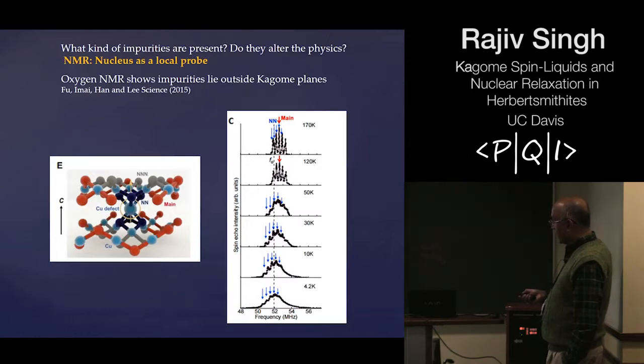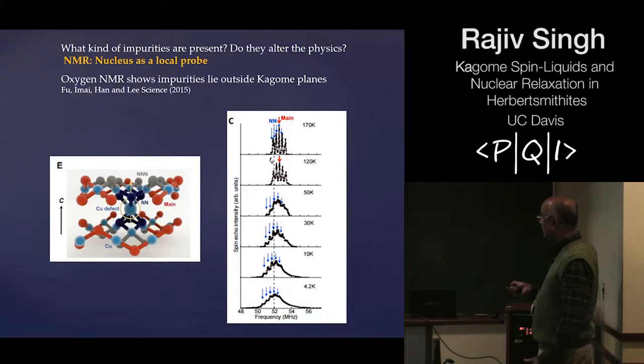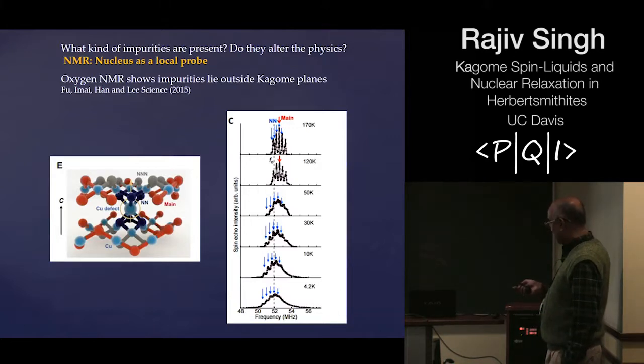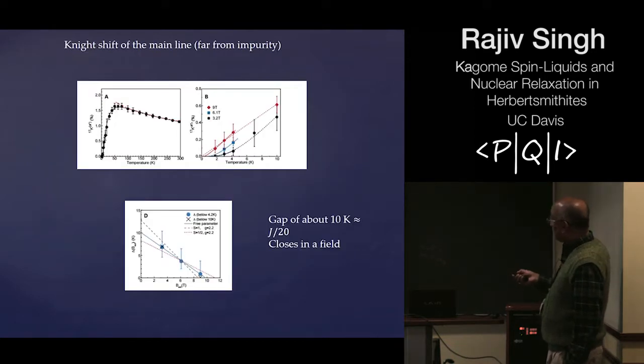And suppose we do an oxygen NMR, then the oxygen spins which are right next to this defect will show a slightly different signature. The oxygens which are second neighbors or next nearest neighbors will show slightly different signatures, and the argument of Imai and collaborators is that oxygens which are further away from the nearest neighbor give a separate signature. So these they call the main line, that is mostly looking at the pristine Kagome behavior, and in the NMR spectra you can separate out these nearest neighbors and the next nearest neighbors. You know what their count should be and what their intensity should be from the main line. So one can just focus on the main line over here, and one can then look at the shift associated with this main line.